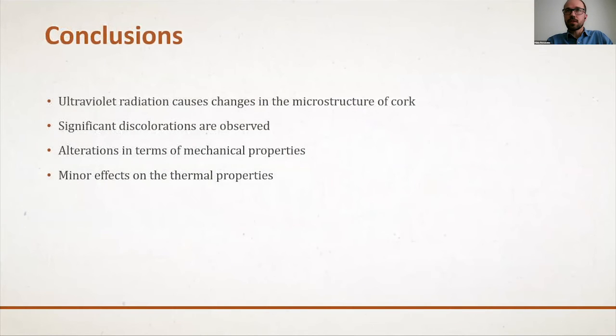So the main conclusions of this work is that ultraviolet radiation causes changes in the microstructure of cork, which reflects in its macroscopic properties. The changes are clear in terms of discoloration. Regarding mechanical properties, the compressive strength increased, although there is a clear loss in terms of viscoelasticity and compressibility related to the suberin content. And the degradation of its capacity as an insulator was observed, but the magnitude of this effect is almost insignificant, at least for the time of exposure that we employed in our experiments.